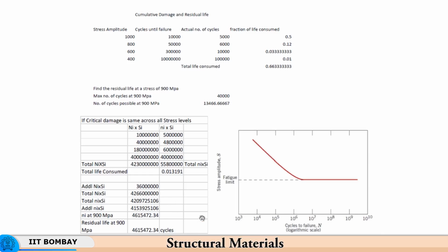So, it all depends upon how you have calculated, what assumption you have used. Usually Miner's rule is used because it is more logical, one would expect more damage to get accumulated, and therefore one would accept cumulative damage taking place. Now, these are all linear additions, the damage which has taken place under different situations of stress and number of cycles is being linearly added, which gives us a perfectly acceptable estimate of the residual life.